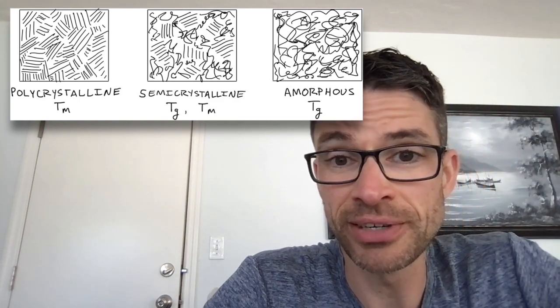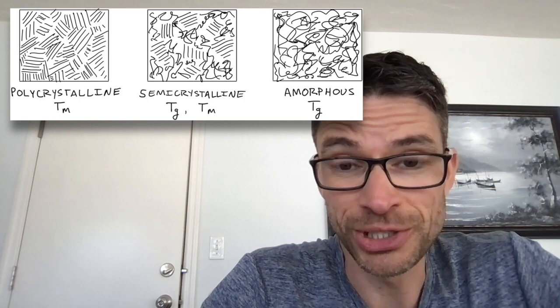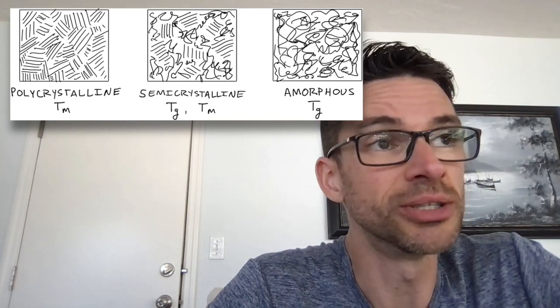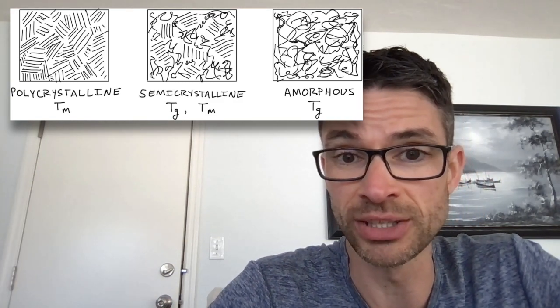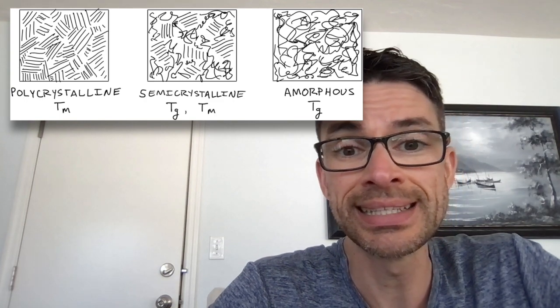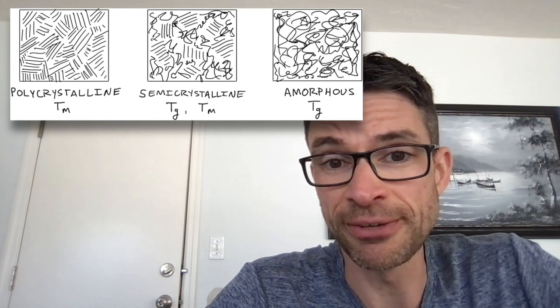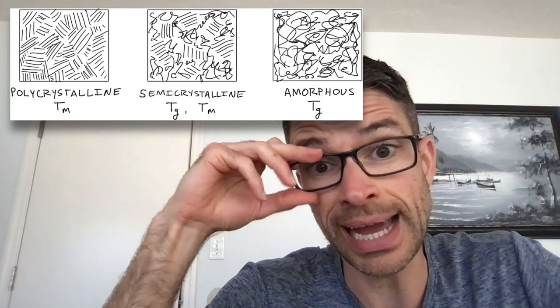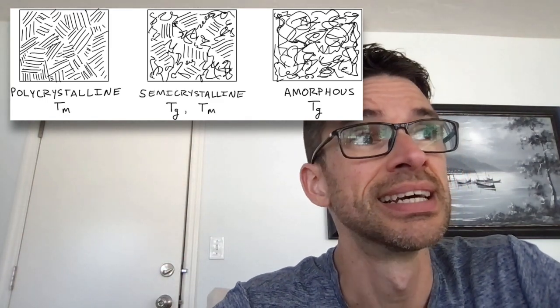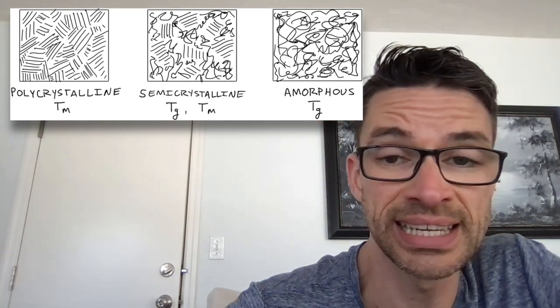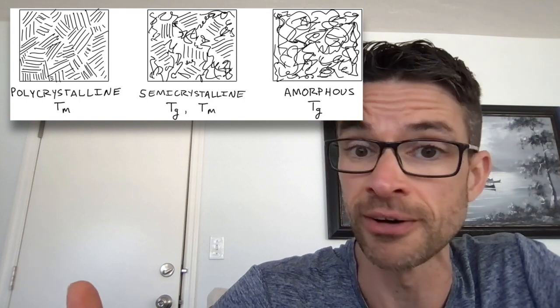Crystalline segments have a transition called the TM, the melting temperature. The melting temperature is associated with a latent heat — it's the amount of energy you need to put in to break all the van der Waals bonds in the crystal structure. That is the main phase transition; it's a first-order phase transition, meaning there's an abrupt change in properties like specific volume, density, and other properties associated with condensed phases of matter.